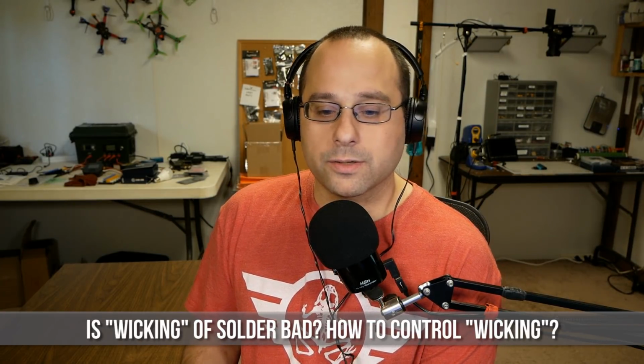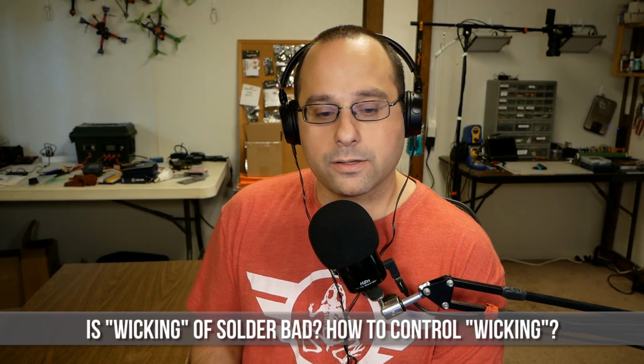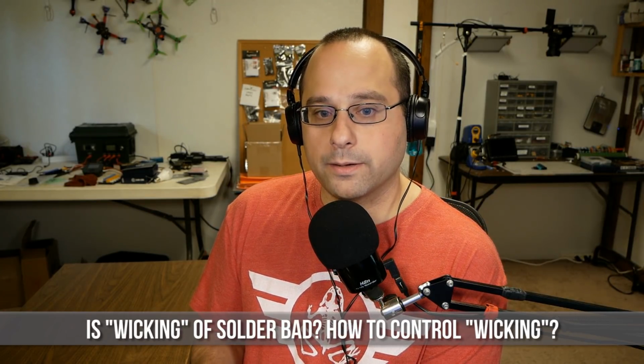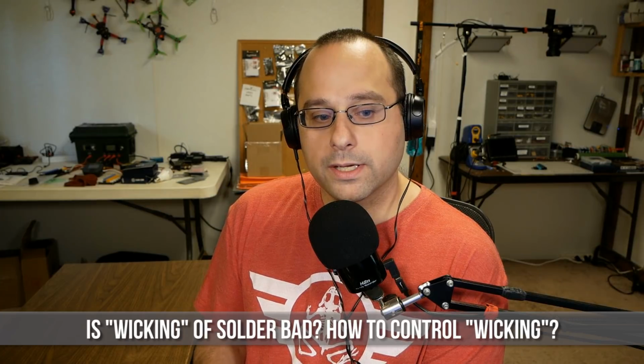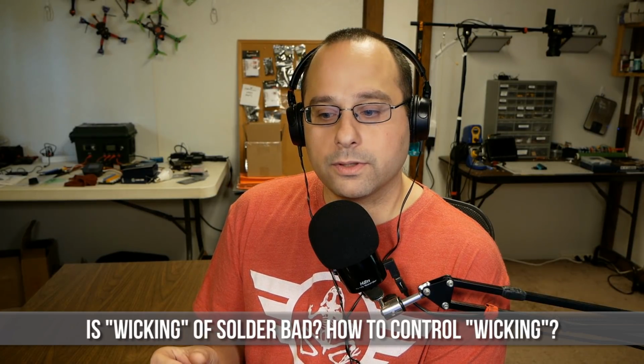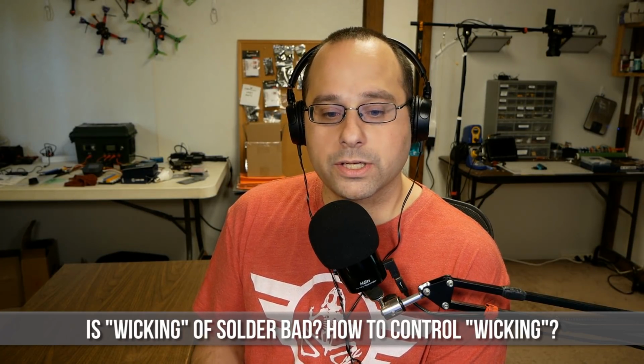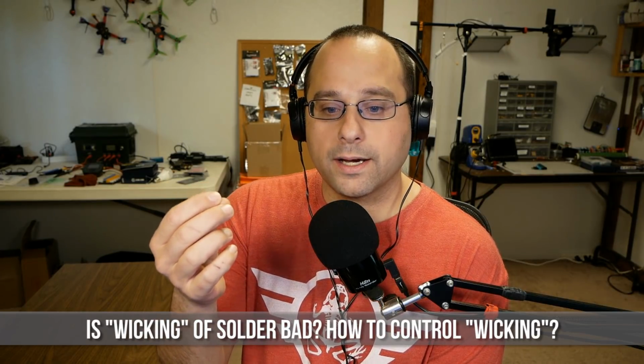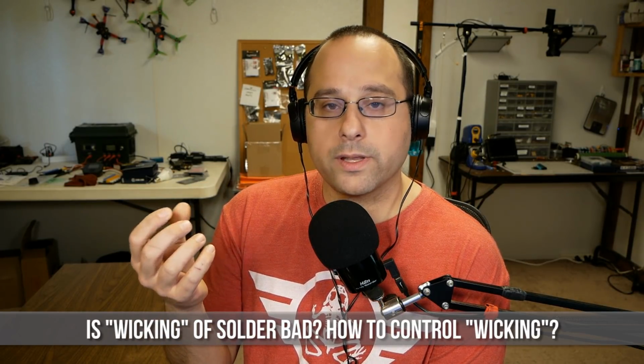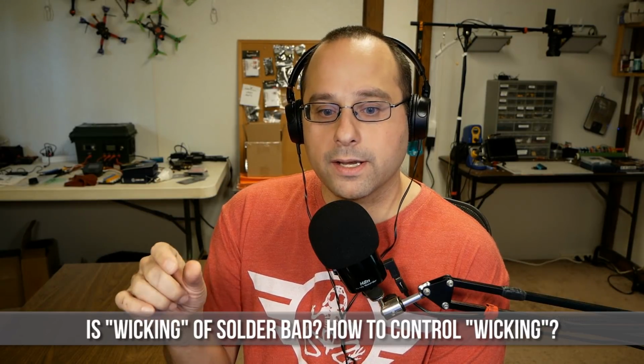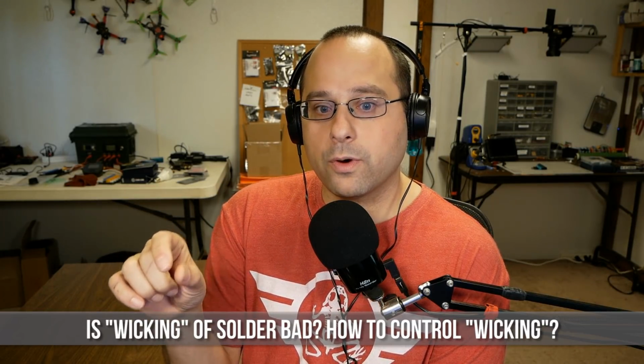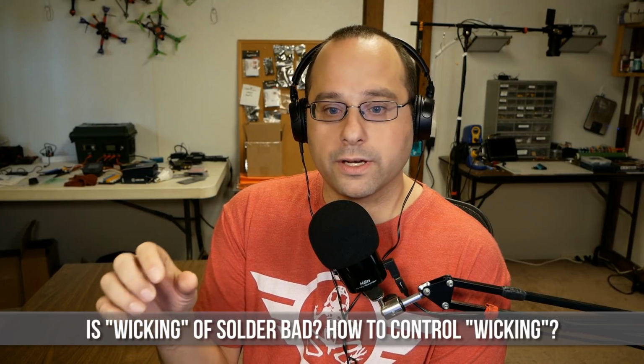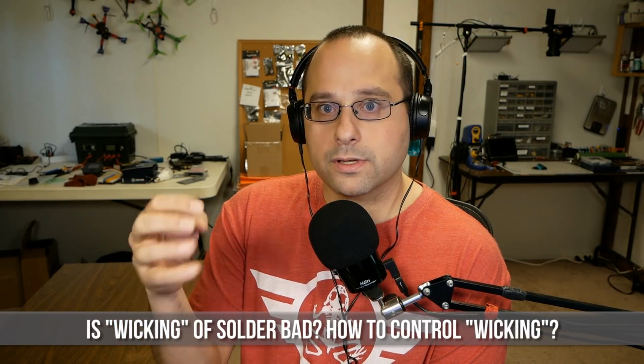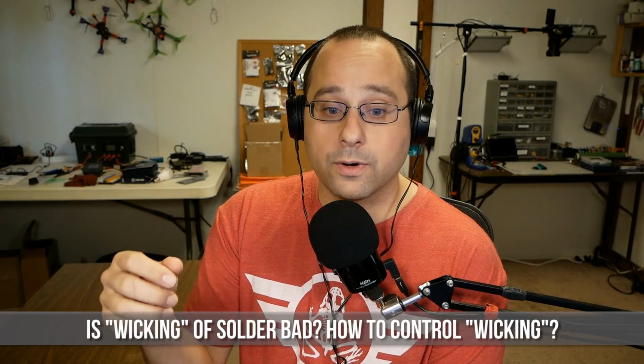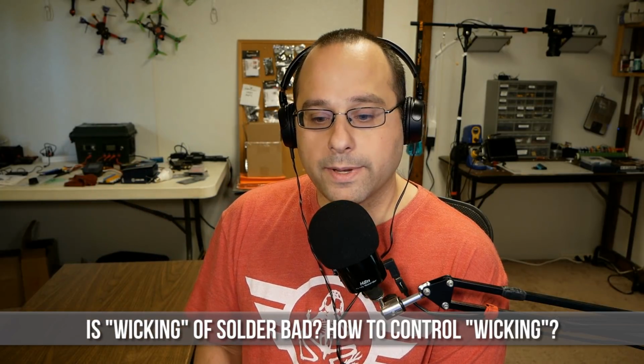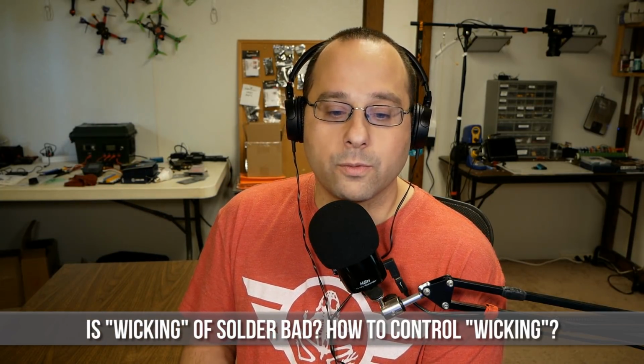Right. Now, there's something that we sort of touched. We didn't touch on it so much as we brushed up against it, maybe, and that is the question of wicking. So a thing that people asked about was that if you're trying to solder the wire, and when you're finished, a lot of the solder has wicked up into the wire, and the way this will manifest, if you guys don't know what I'm talking about, is that when you're done, there will be a stiff part of the wire, maybe 1/8 of an inch or 1/4 inch even up past where the joint is, where the solder has wicked up into the wire and solidified. And that's not good. Why is that? First of all, why is that bad, Randy?